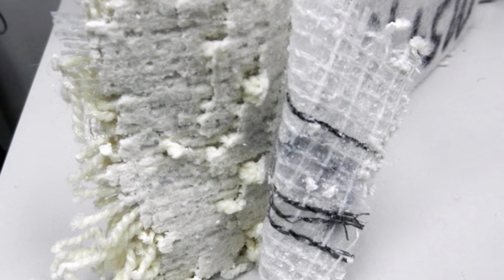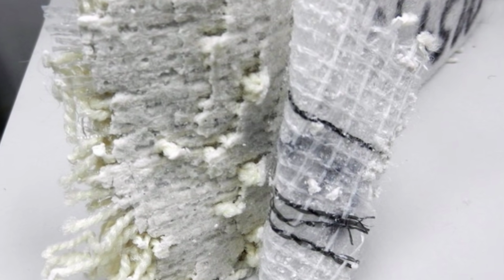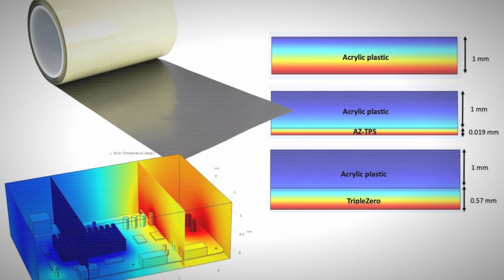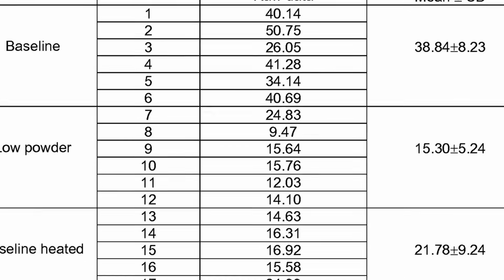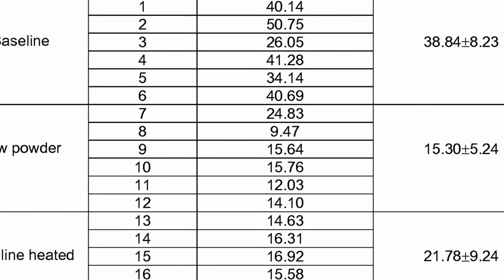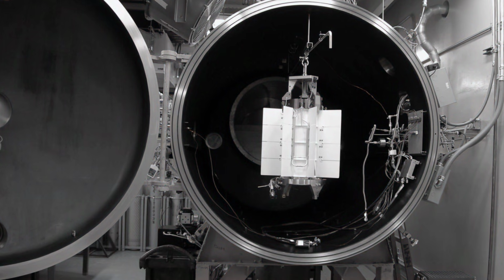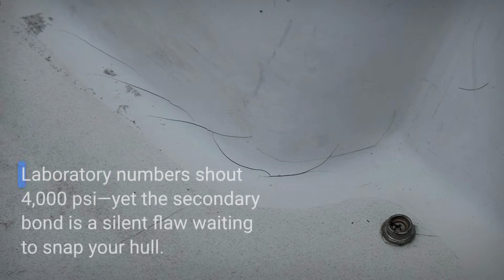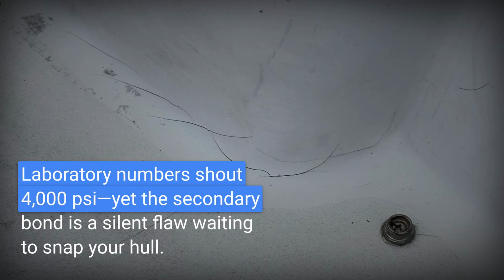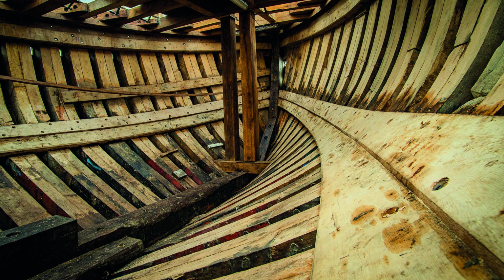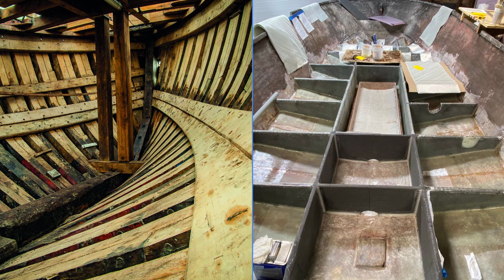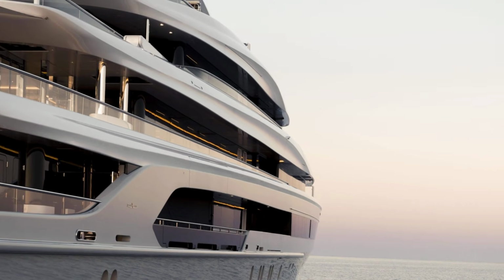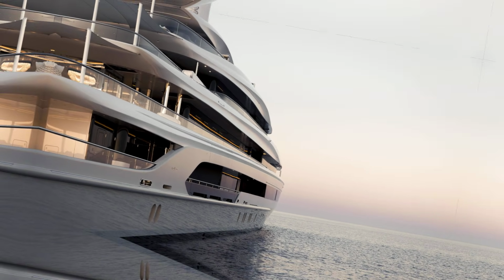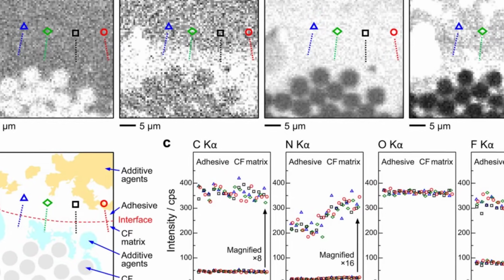The chemist's bench is littered with failed coupons, some delaminated after a simple water soak, others peeled apart with a groan that echoes the hollow plasticky thump of a lined hull. The numbers are cold, 1.8 megapascals for the secondary bond, sometimes less after thermal cycling or a bit of moisture. That is the silent flaw hiding beneath the glossy finish. The difference between a true structural skeleton and a high-priced IKEA cabinet glued to a hull is measured not in showroom stiffness, but in the molecular handshake at the interface.